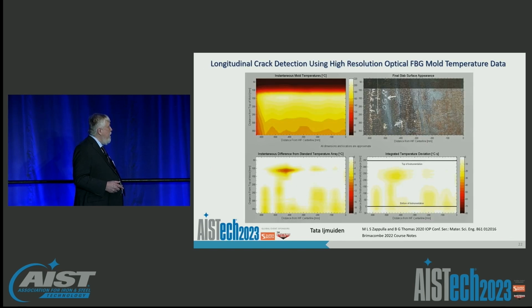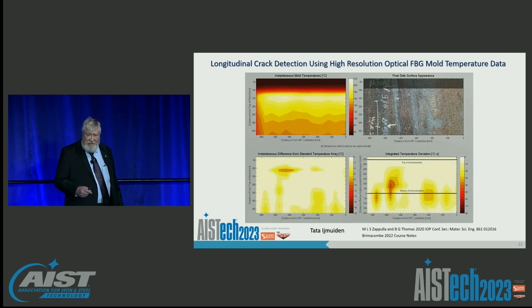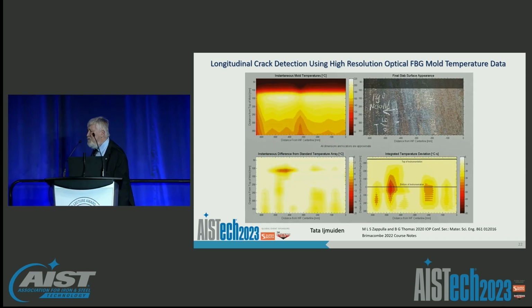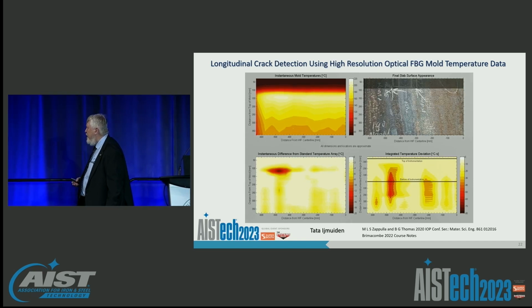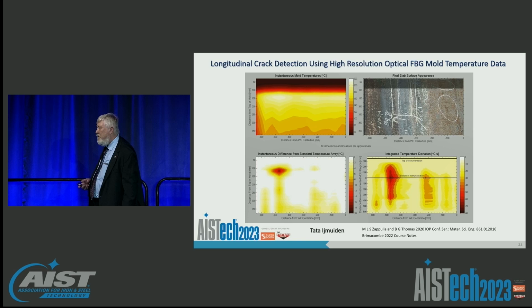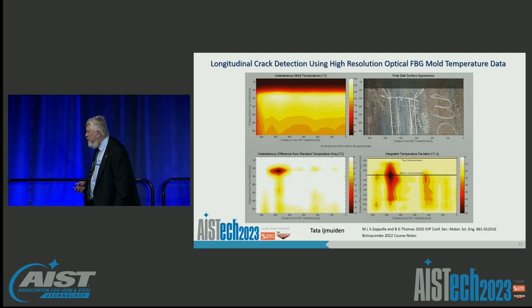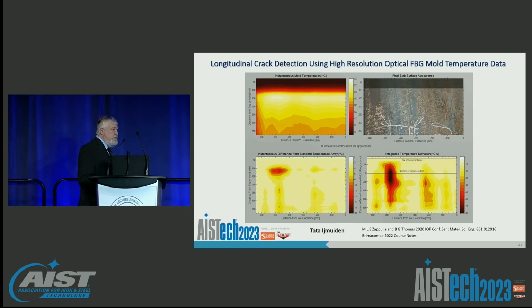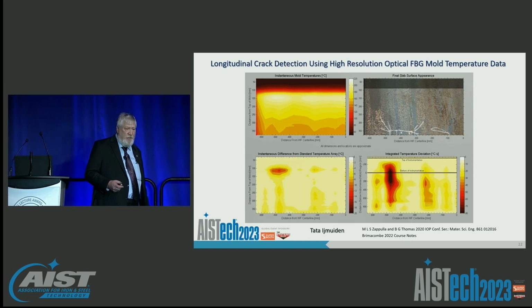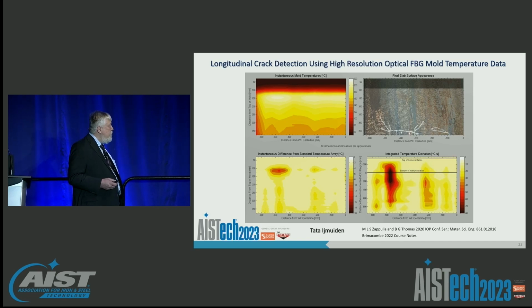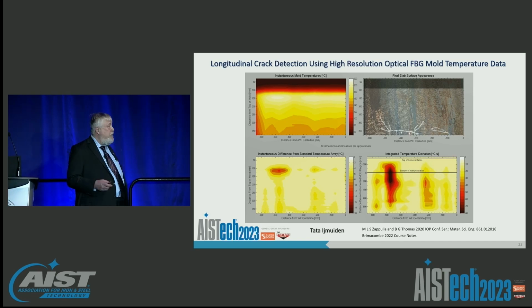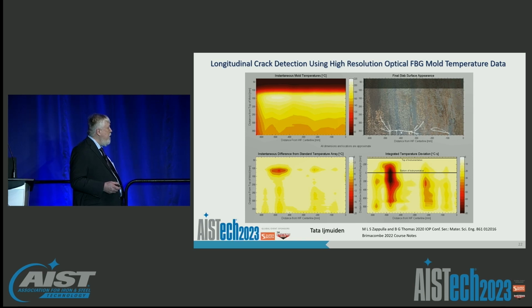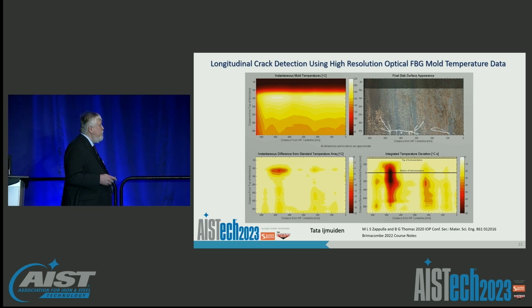So this is actually a slide that Brian Thomas put together, and it shows how these fiber optic mapping systems can be modified and interrogated to identify high-risk regions for longitudinal cracking, for example. Up to this point, conventional breakout systems did not have the resolution to do this type of measurement and sensing well. But these new high-density fiber optic systems are very good at detecting these asymmetries and anomalies. And given that these longitudinal cracks can have very narrow spatial width, it requires high-density measurements in order to identify them.